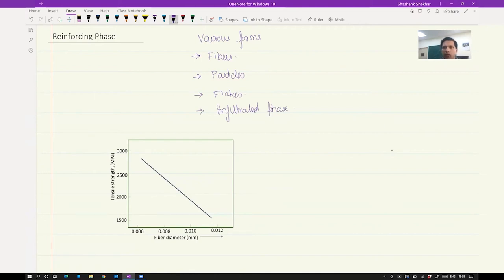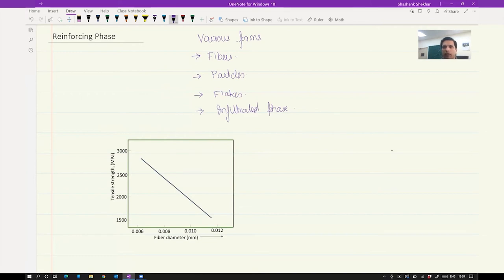Fibres are usually tubular, rectangular, or sometimes hexagonal, but importantly they have a constant cross section and can bear the majority of the load. The filament structure of fibres is mostly defect-free — very thin metals such as whiskers are also dislocation-free — so fibres have very high strength, which is why they can be used as reinforcement. Fibres can be continuous or discontinuous. If the thickness is very small — with diameter as small as one micron — they are called whiskers. Thicker fibres are not whiskers but can still provide good reinforcement.